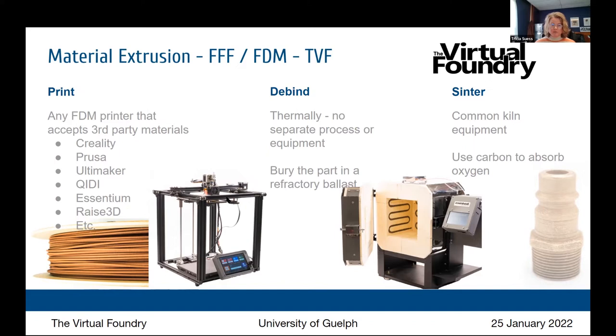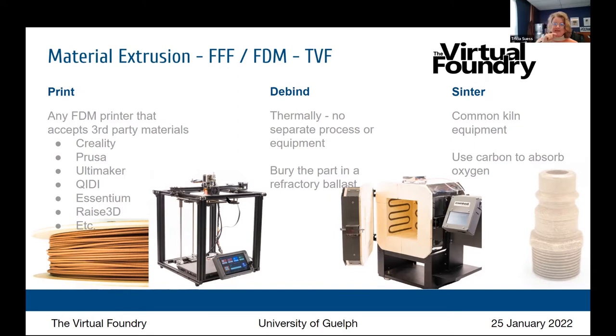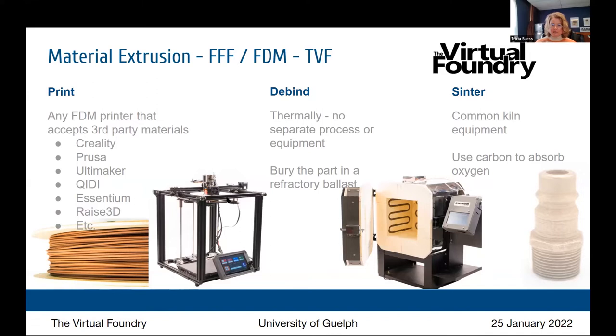Because the part is buried in powdered support material, there are fewer design limitations up front — outcroppings are fine. If you're printing something that requires supports, you can use any support material you normally would, including regular PLA or PVA (a water-dissolvable support), or just more filament if you only have a single-extrusion 3D printer. You then break the support material away, and the refractory ballast provides the part shape. Any shape is possible, including bridging, because you can fill in that space with refractory ballast. We need to support these shapes because as the binder leaves and the metal particles begin to join together, the part shrinks — so pieces sticking out would droop without support.